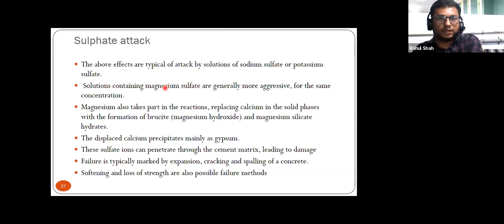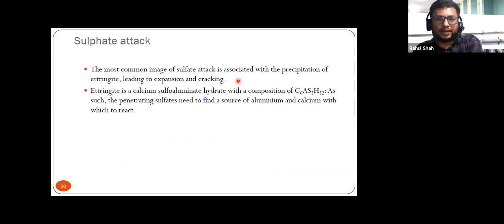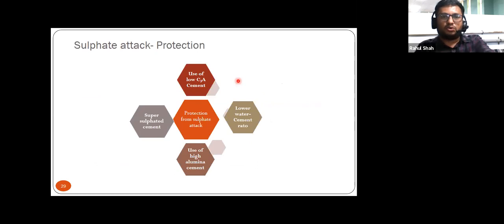So this particular attack, sulfate attack, is generally by solution of sodium or potassium sulfate, right? Sometimes magnesium sulfates are also there. So depending upon it, this all type of sulfates affects the concrete very badly, right? So it will damage the cement matrix. Typically it will expand, it will crack, and generally spalling of the concrete may occur. So generally loss of strength is evident from the sulfate attack, and ettringite is a common source of issue in this particular reaction. So how to protect this, right?